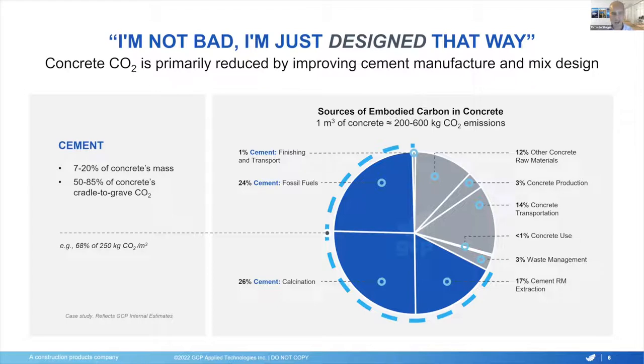In this slide, I'm presenting a case study from a cradle-to-grave analysis of a concrete mix, where you can see the breakdown of the sources of CO2. Typically, you would see that the main source of CO2 is clearly cement in concrete, because cement has a component of CO2 coming from burning fuels, a component from the chemical reaction — decomposing calcium carbonate into calcium oxide and CO2 as a by-product in the clinkerization stage — and then other sources like grinding. We are going to focus on this part of cement today.